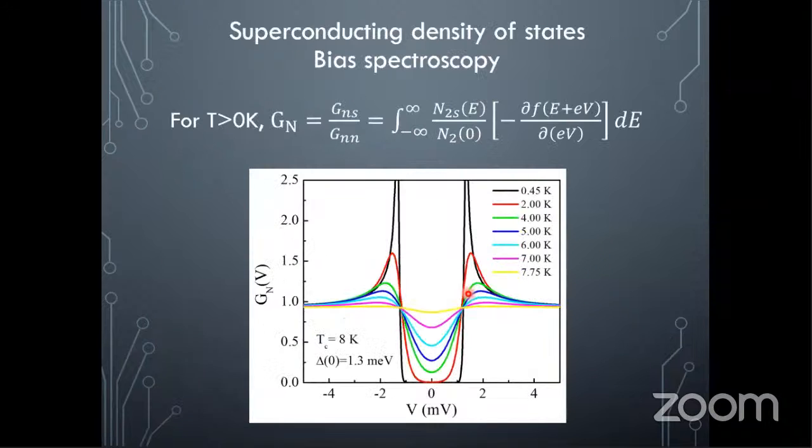And we generally find that for superconductors like niobium nitride, molybdenum germanium, or say niobium diselenide, etc., the variation of the BCS gap follows the theoretical prediction.